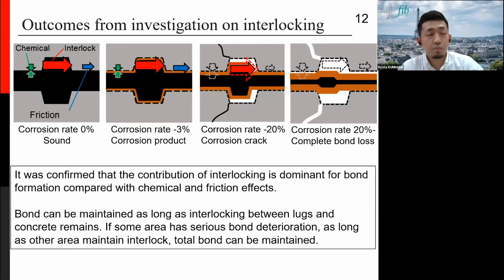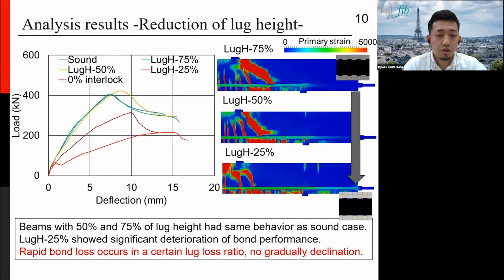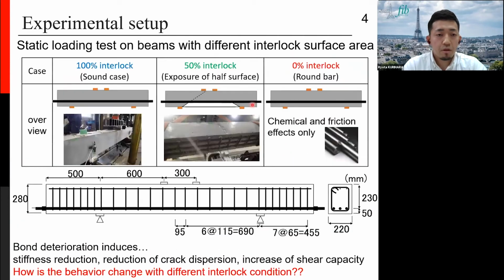Okay, the compressive strength of the beams is about 40 megapascal, and the tensile strength is 3.9 megapascal. The concrete cover means the concrete at the bottom part, under the main rebar. In general, it doesn't contribute to the structural performance.